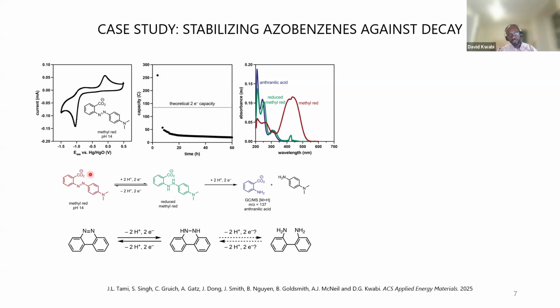We took this molecule, we put it in a flow battery, and we discovered that it actually undergoes very rapid capacity fade over time. If you look at the x-axis here, this is on the order of a day or two. We lose almost all of our capacity in our battery as we cycle it.